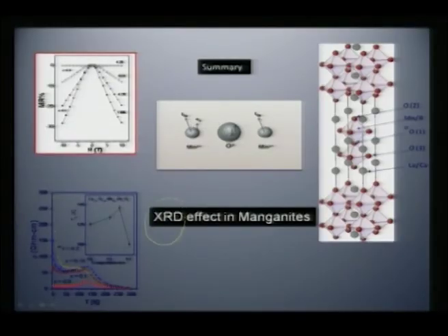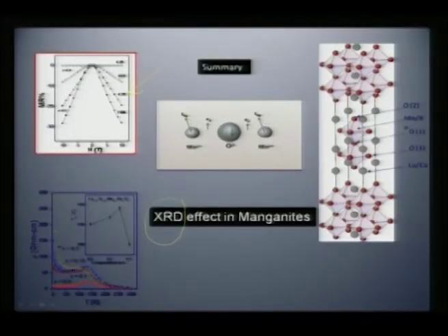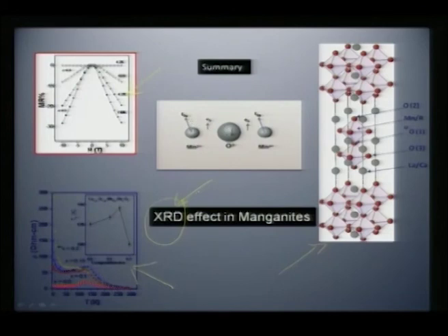So, to conclude, we have seen the XRD effect in these manganites, which I call the genie in these manganites, and we have taken an example to see how this manganese 3 plus 4 plus core, when it is disturbed, can still bring about a very rich chemistry, especially with substituting ruthenium, and we have seen how the dimensionality works, especially when you substitute ruthenium, where you twist the spins along the C axis. So, in essence, manganites are a very interesting set of compounds that provide rich chemistry and physics, and there are a lot more examples that we can study along the XRD effect in manganites.